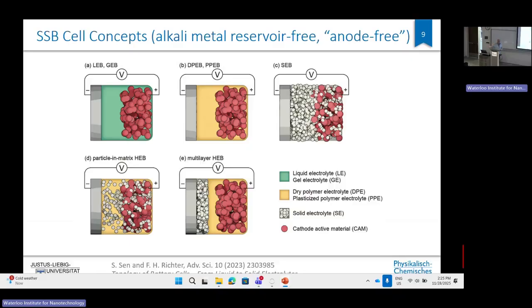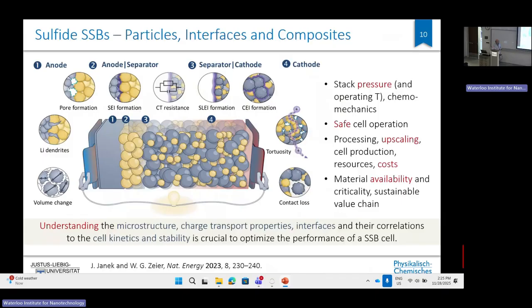It's also easier to process because processing 10 micron thin or 20 micron thin lithium foils is pretty difficult, in fact, and not cheap. Whether it really works is another question, but I think it's a great idea, of course, to have all the lithium here and in the first charging step, just to place lithium here and to cycle it. Of course, what you need in order to have a good cell is 100% Coulombic efficiency. You should not lose any lithium. And this brings me, of course, to the first point.